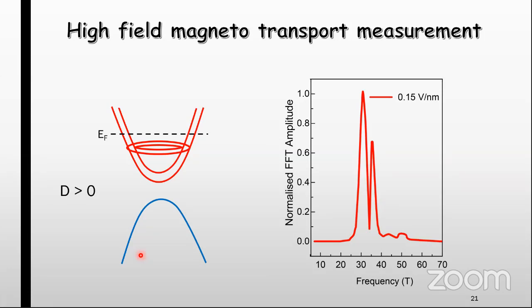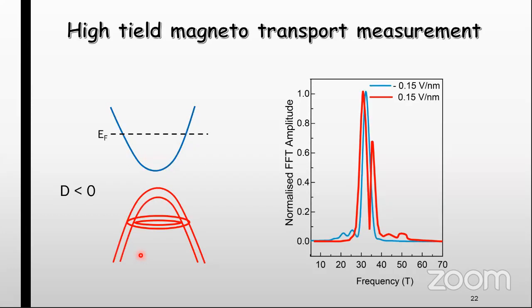Then we flipped the direction of the electric field and again performed this measurement, and this time we found there is only a single frequency, when there is no splitting in the system. So this is also consistent with the theoretical prediction.